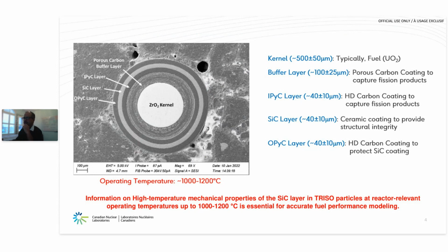The same image now shows basically different components of the particle in the cross section. Kernel, which is typically nuclear fuel, uranium oxide, is 500 plus minus 50 microns in diameter. And it is coated with a buffer layer, which is about 100 plus minus 25 microns. And it's a porous carbon coating, which is there to capture any fission products, because like this is fuel, during its use in a nuclear reactor. There will be fission products, and the idea is to capture those fission products in this porous carbon coating around